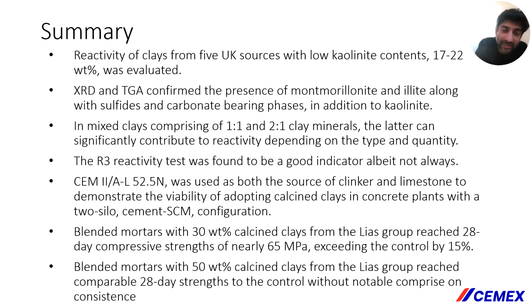CEM II/A-L 52.5N was intentionally used as both the source of clinker and limestone to demonstrate the viability of adopting calcined clays in concrete plants with a 2 silo, cement and SCM configuration. Blended mortars with 30% calcined clays from the Lias group reached 28-day strengths of nearly 65 MPa, exceeding the control by 15%. Blended mortars with 50% calcined clays of the Lias group reached comparable 28-day strengths to the control without notable compromise on consistency.